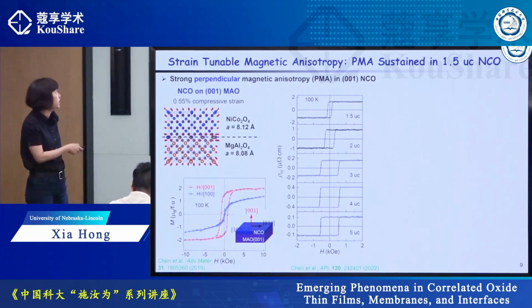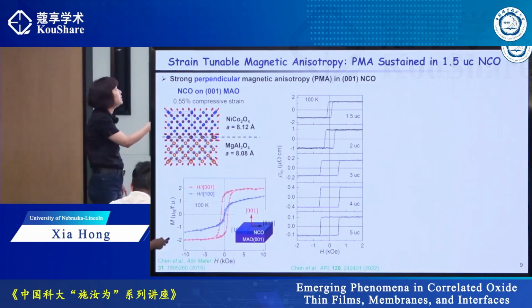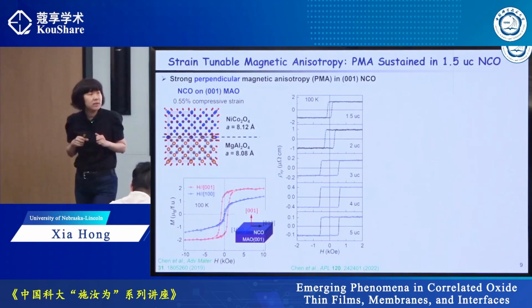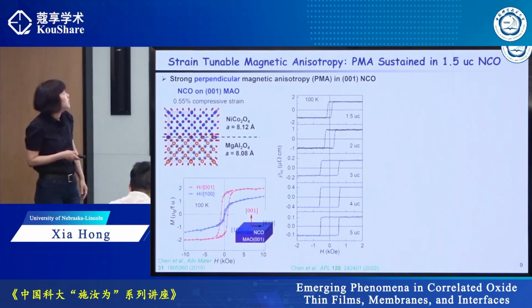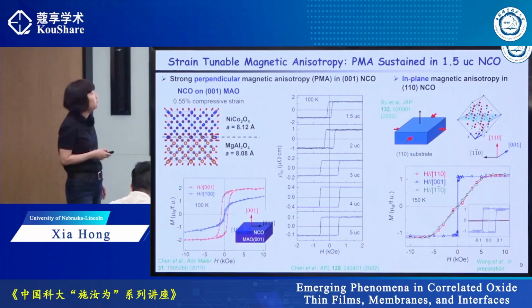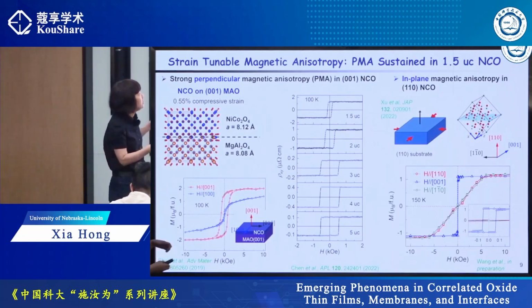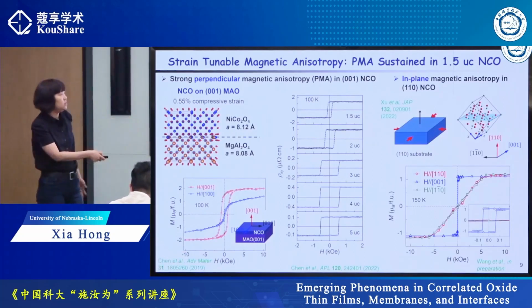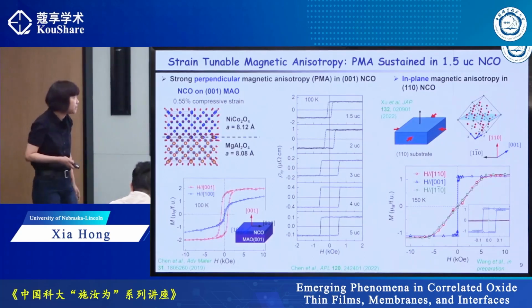So we show here the anomalous Hall resistance as a function of a magnetic field, and you can see down to 1.5 unit cells, it has a very squarish hysteresis. And if you grow in the other direction, so it's compressed actually in plane, the magnetic anisotropy becomes in plane. So it's really tunable by strain.